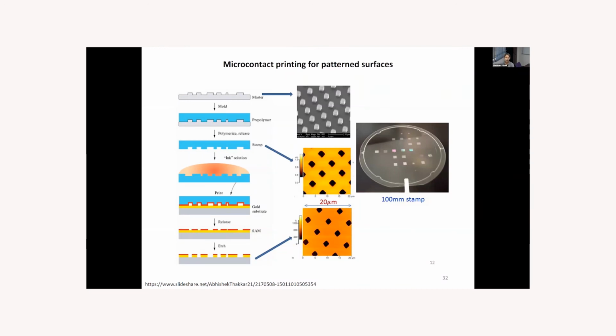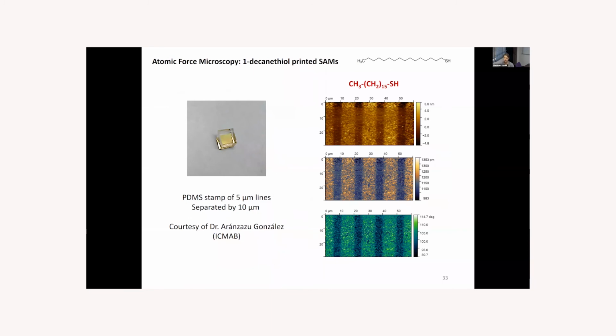And we have prepared the self-assembled patterned surfaces of molecules of methyl groups. As you can see here, by AFM images, you could see that actually the lines were nicely formed. We used 5 micrometer lines of molecules separated by 10 micrometers of free space. And we obtained the stamps thanks to Dr. Gonzalez from ICMAB, who prepared them for us. So we are very grateful, and we are happy we could create these patterned surfaces.